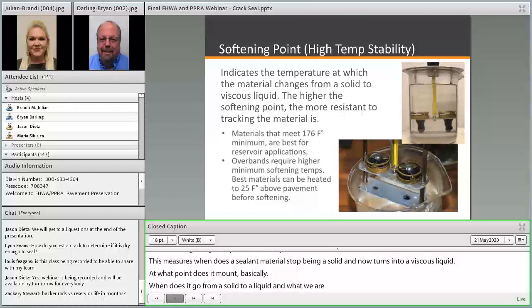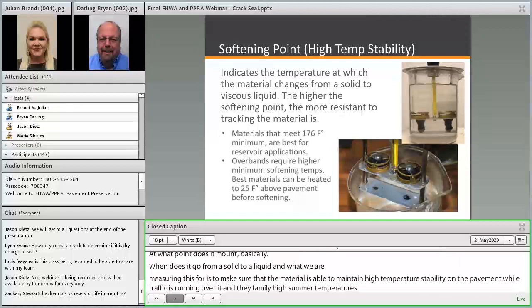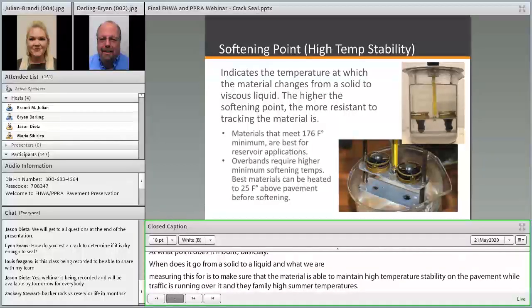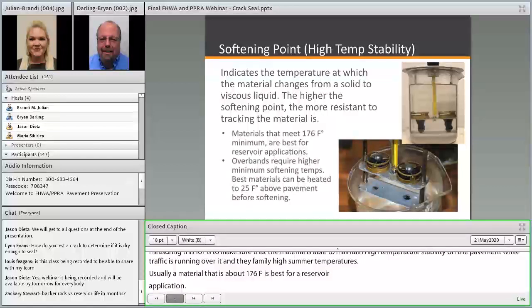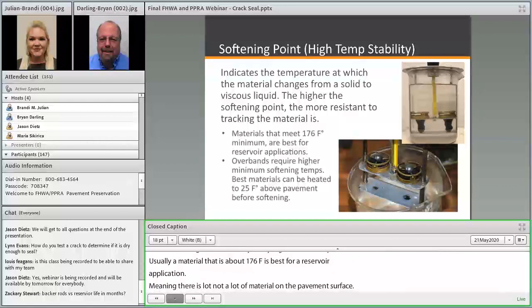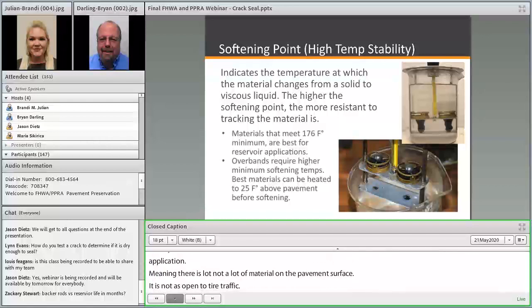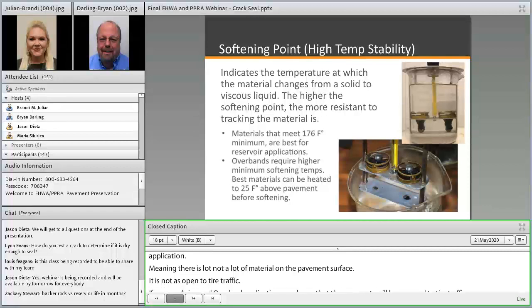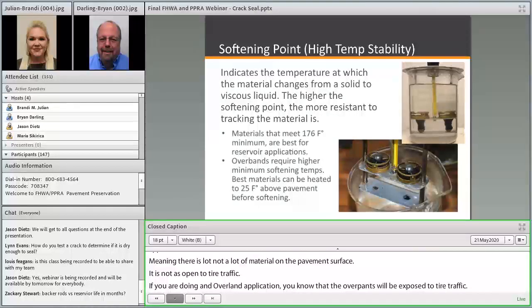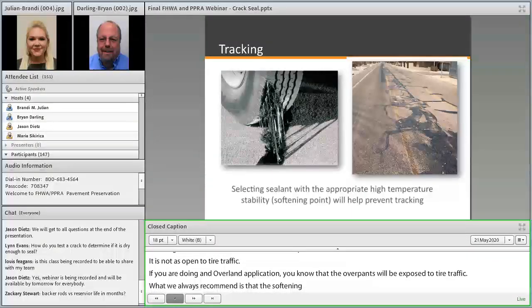Usually a material that is about 176 F is best for a reservoir application, meaning that there's not a lot of material on the pavement surface. It's not as open to tire traffic. If you are doing an overband application, you know that that overband is going to be exposed to tire traffic. What we always recommend is that the softening point be 25 degrees higher than the pavement's highest temperature in the summer. That way you can ensure that that sealant will maintain high temperature stability in the summer months.